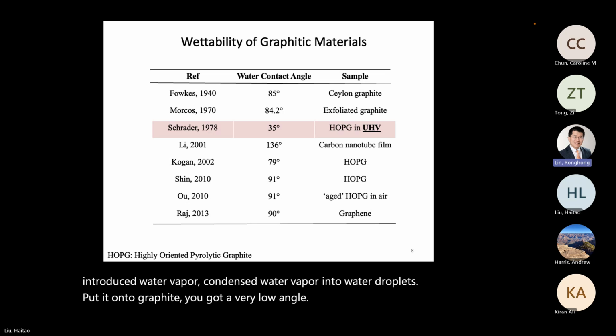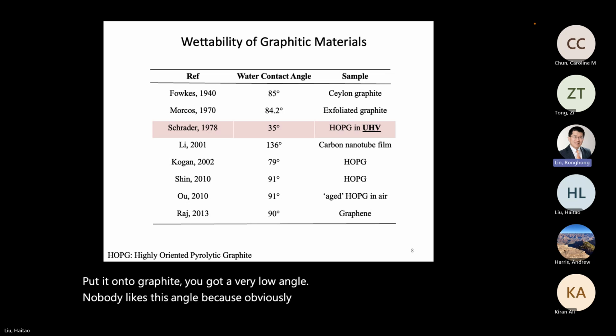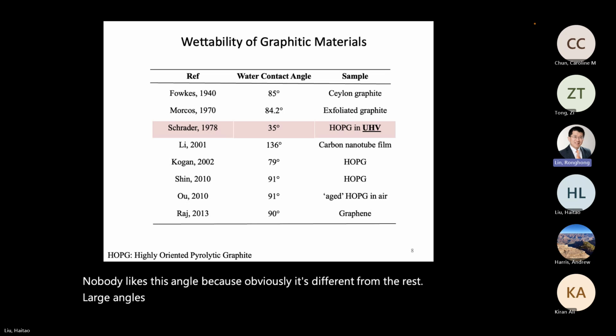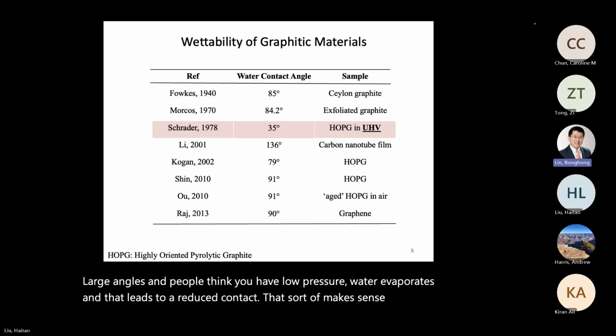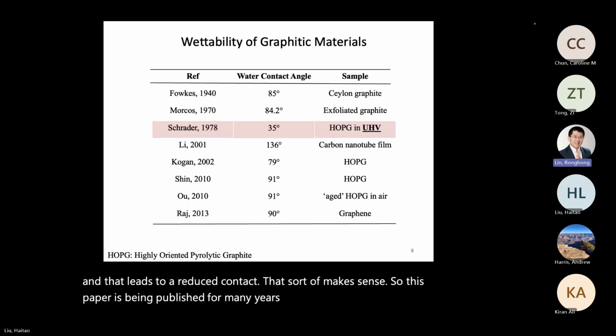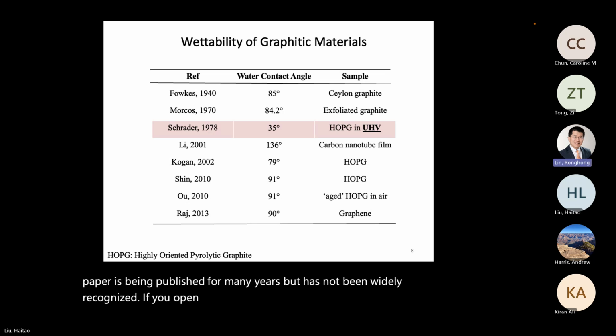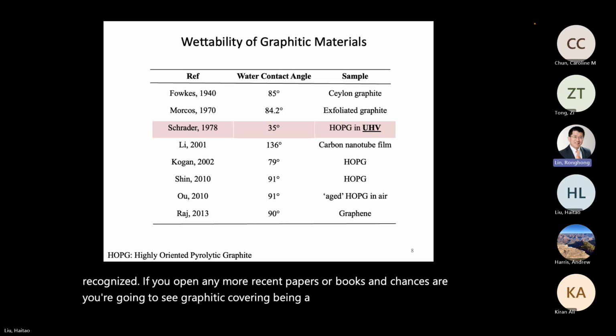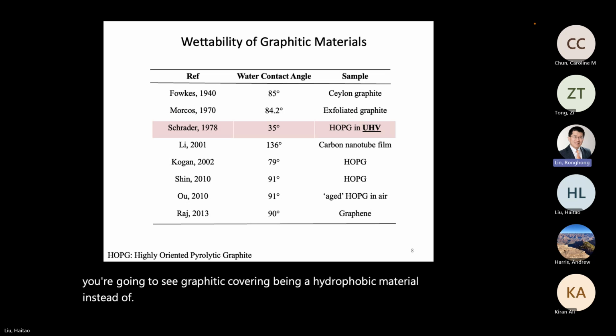Nobody likes this angle because obviously it's different from the rest, large angles. And people think, oh, you have low pressure, water evaporates, and that leads to a reduced contact angle. That sort of makes sense. So this paper has been published for many years, but has not been widely recognized. If you open any more recent papers or books, chances are you're going to see graphitic carbon being a hydrophobic material instead of a hydrophilic material.